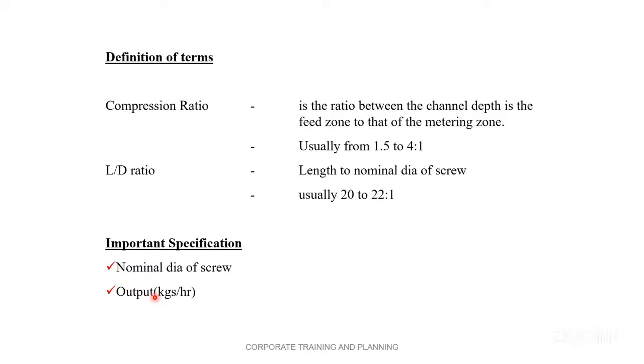Channel depth at the feed zone divided by the channel depth at the metering zone, usually from 1.5 to 4 to 1. This is the compression ratio. Therefore, suppose there is 1 millimeter at the metering zone, there may be 4 millimeter in the feed zone, like that. So it varies from 1.5 to 4 in the feed zone divided by 1 of the metering zone.